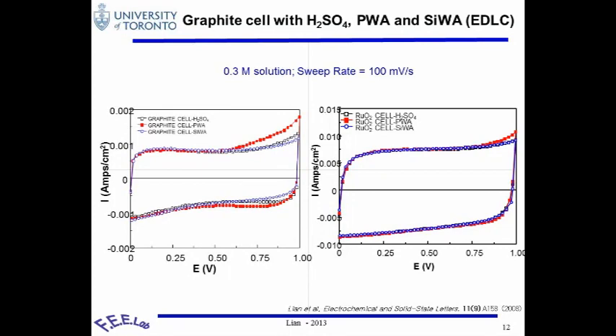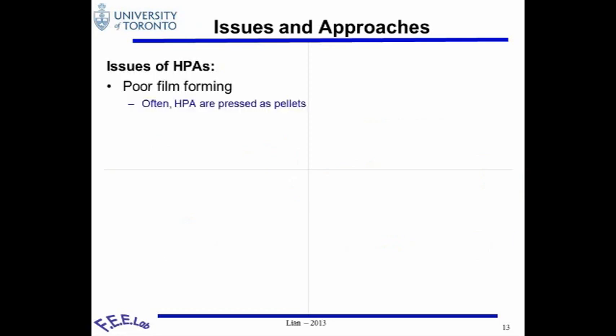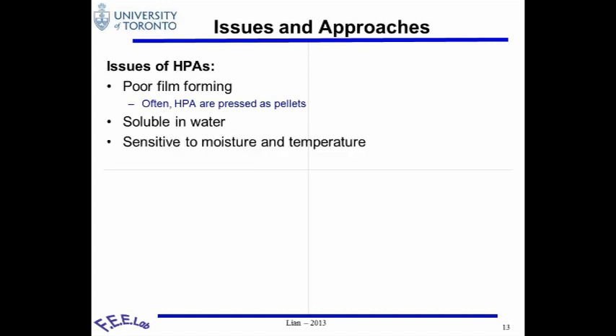With this in mind, we start to develop some solid electrolyte materials. The problem we run into is that for the HPAs, they are salts, so they cannot form a film. This is something we have to look into, and all the results in the table showing conductivity were actually done through pellets. In order to make it more viable for devices, we have to address that problem. The second problem is they are soluble in water, so they're very sensitive to moisture in the environment. These are the things we need to overcome.